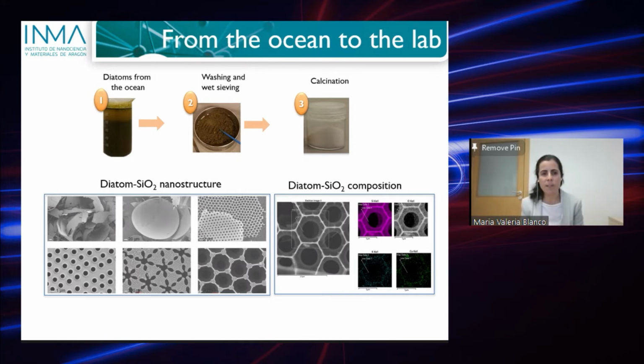diatoms. And looking with the SEM, you can see this really nice nanostructure that they present. And you see different nanostructures because these algae are composed of layers of silica walls, and each layer has some nanometer thickness. So this is really something we wanted to look into. On the right side of the slide, you can see some EDX mapping of these diatoms, and you can see that the major component is silicon together with oxygen, and we have some trace amounts of potassium, calcium, and magnesium as well that are incorporated through this biomineralization process together with the silicon.